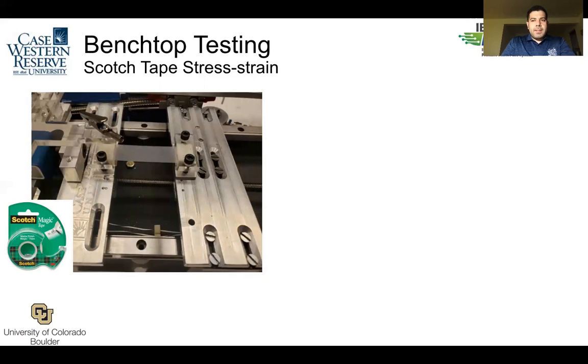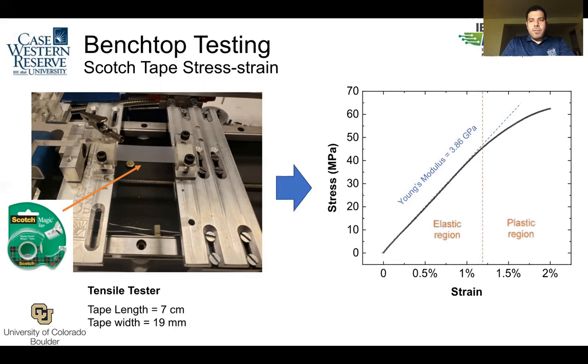We double clamped it, and this sample you see has a length of 7 centimeters and a width of 19 millimeters, or nearly 1 inch. And using a force gauge and the LabVIEW software, we plotted the stress strain curve, as you see in this curve. So this curve tells us what the elastic limit of a Scotch tape is, and you see it's very soft. The Young's modulus is 3.86 gigapascal, and the elastic region is nearly 1.25%.